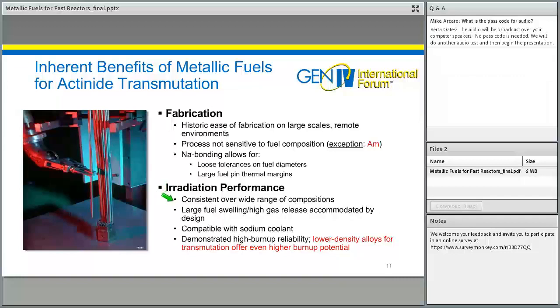In the irradiation performance area, I'll show a little bit on this later, but what we've shown over decades of experience with metallic fuel is the performance tends to be very consistent and quite similar over quite a range of compositions and deviations in a metal fuel alloy. So you don't have to keep content controlled within a very narrow band in order to know how your fuel is going to perform. Metallic fuel is entirely compatible with sodium. In fact, there's bond sodium on the inside of the pin, so it makes for the possibility, if you do have failure, of running beyond cladding breach in a very benign way.